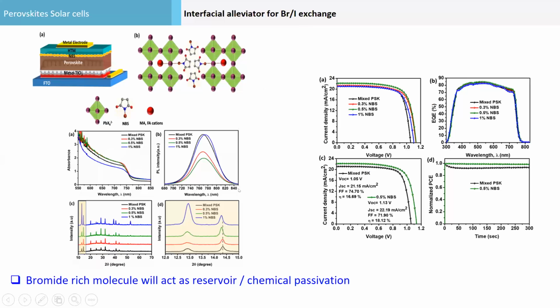Similarly, recently we are also doing NBS. NBS is very good because it oxidizes and it produces free radicals. So instead of iodine, it will be bromide, which will passivate the surface. And there's always unreacted lead on the surface. So the unreacted lead can react with an excess of halide, NBS or imidazolium iodide, and will form a compound with lead iodide. So this also we have used, NBS recently. This is also working slightly, from 17% we go to 18.2%. They were also increasing the stability.